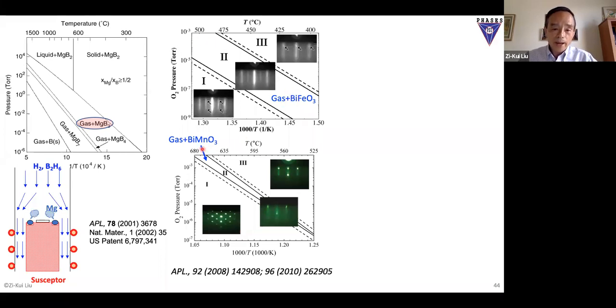However, bismuth manganite is so difficult. Remember, this is -9 to -3, right? This is -7 to -3, and the range here is half an order of magnitude. This is 2 orders of magnitude, half order of magnitude. So it's very difficult to grow phase pure bismuth manganite because the window is so small.